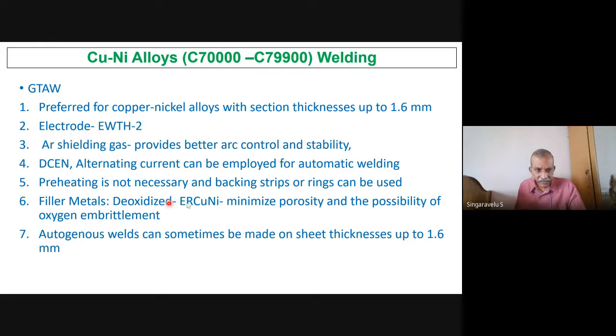Filler metal should be a deoxidized one, which eliminates porosity and the possibility of oxygen embrittlement. The wire has to be ERCuNi, completely deoxidized. Even sometimes this goes by double deoxidation. Okay, autogenous weld can be made up to 1.6 mm thickness.